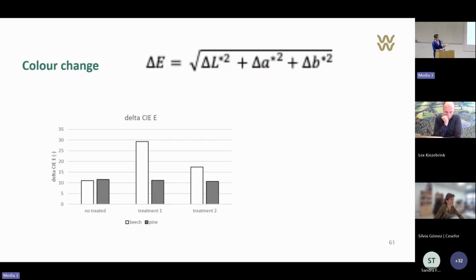Here you can see the samples after the weathering test, exposed before and after weathering, treated and untreated. Here you can see the color changes. What was most important for us, after measuring the CIELAB and gloss, was to see materials which are not really changing in appearance. In our case, the pine seems to be much more stable under artificial weathering than the beechwood.